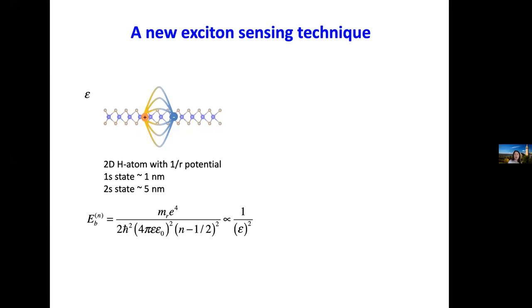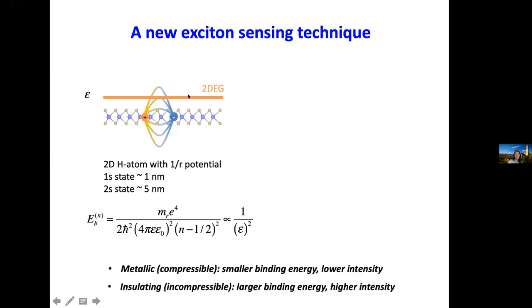So the exciton binding energy in the simple picture scales as the dielectric constant of the surroundings to the -2 power. And the oscillator strength will also scale with the dielectric function of the surrounding medium. So if we put our Moire system next to it, and if it's metallic or compressible, then we should see a smaller binding energy and a lower oscillator strength for, for example, the 2s exciton.